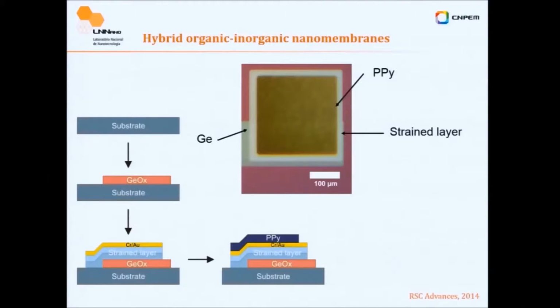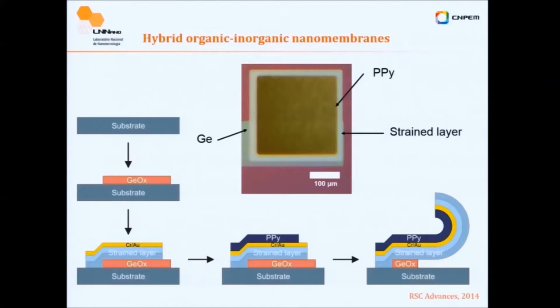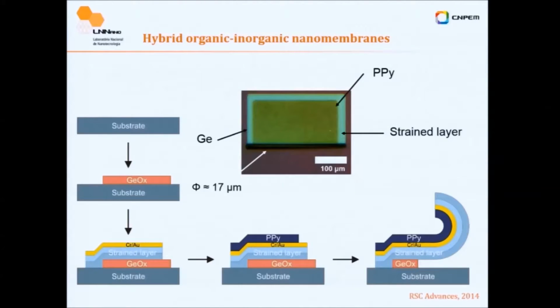So how do we pattern this? We simply create a route where we have the germanium dioxide, an already strained layer and a chromium gold layer, then you polymerize on top. We developed a technique a few years ago so that you can pattern polypyrrole very easily, and this layer can be 50, 70 nanometers, you can go down to 20 nanometers if needed. And then what happens after you remove the germanium dioxide in water, the polypyrrole is embedded inside of the tube.